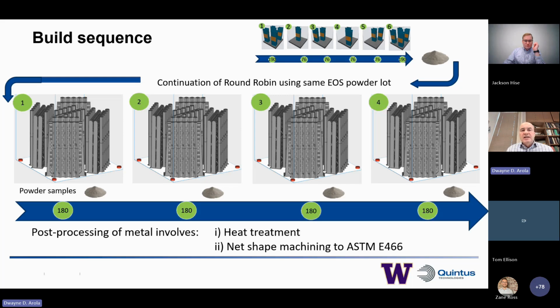So you're looking at a slightly different oblique view here. Each one of those builds rendered a group of almost 200 specimens in the horizontal and vertical orientations. That was sent to the University of Washington along with a powder sample. So what we could do is track the powder chemistry and introduction of contaminants if it was relevant. Okay. So each partner built a little bit over 700 total specimens.